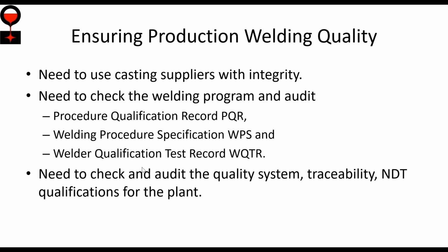If you forbid me from welding the casting, then I'm unlikely to make your castings. One of the common things was in the API standards, the highest level, the highest PSL level, forbade welding. And the only way I know that foundries could do that is they would agree to make 10 parts for you, and the ones that passed without any welding, they'd certify as meeting the high requirement. They'd weld the rest of them, but you were buying all of them, because we really don't have the option of making castings and not being able to finish them to meet your quality standards.